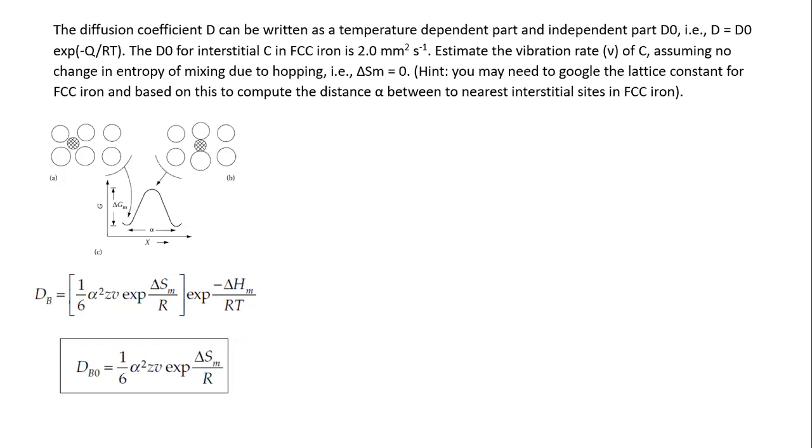But the concentration of vacancies was also very low, right? No, in here we didn't have to worry about the vacancy, because we only need to worry about the number of sites this can hop into. The only case that a site is not available is when another atom, the same atom, is taking this position. So this is going to lead to a reduction of Z. Now your Z star is going to be Z, the original coordination number at a very low concentration, times 1 minus something. In the first order, this is going to be A times X, where X is your concentration.